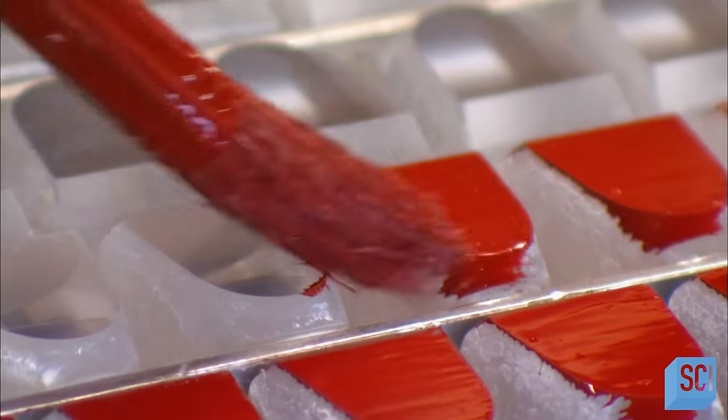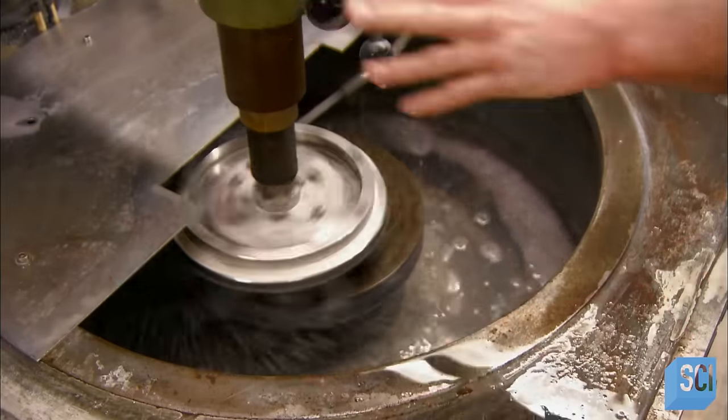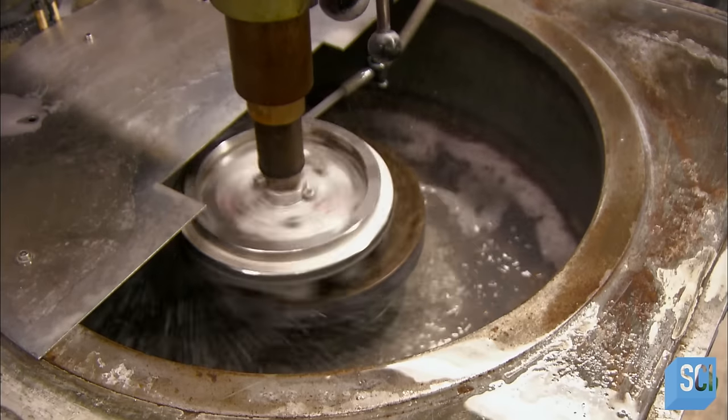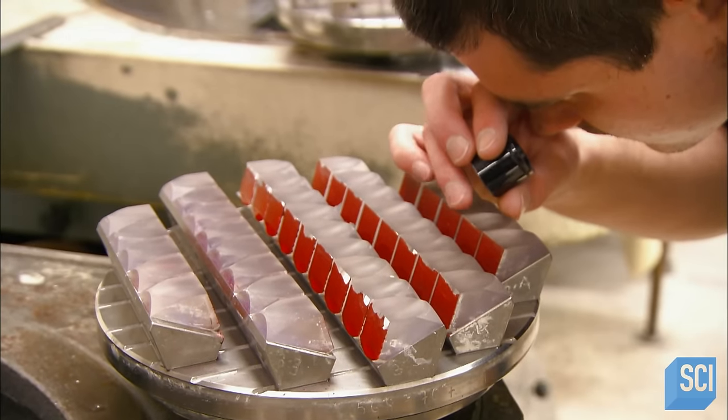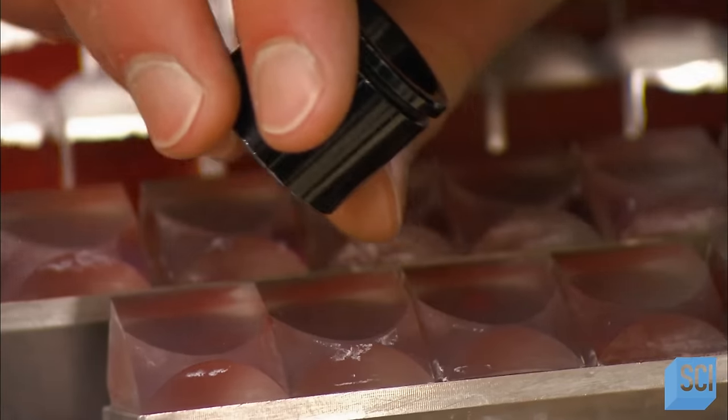Protective paint prevents any dust from contaminating the pristine surface. Grinding with diamond dust removes mere tenths of a millimeter of glass. Polishing with an even finer abrasive removes another one one-hundredth of a millimeter.